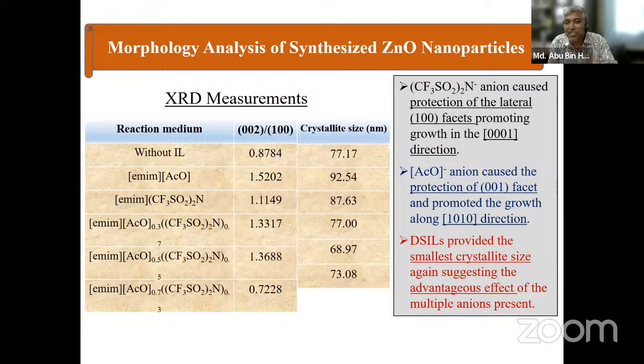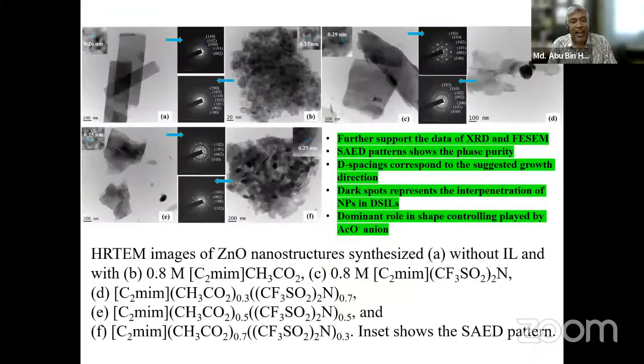That means if we combine these two to prepare double salt ionic liquids, the double salt ionic liquids provided the smallest crystallite size, again suggesting the advantageous effect of the multiple anions present. And when we check the TEM images, the HR-TEM image of zinc oxide nanostructures, we have also found selected area electron diffraction studies here. These further support the data of XRD and FE-SEM, and the SAED pattern shows the phase purity, with d-spacing corresponding to the suggested growth direction. Dark spots represented the interpenetration of nanoparticles in double salt ionic liquids, and the dominant role in shape control was played by the acetate anion.